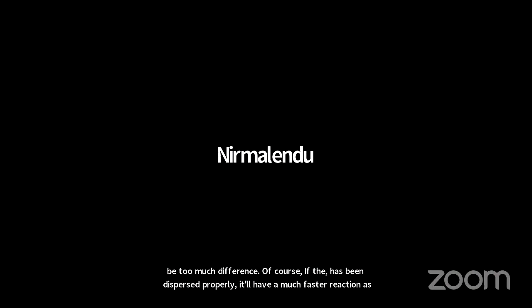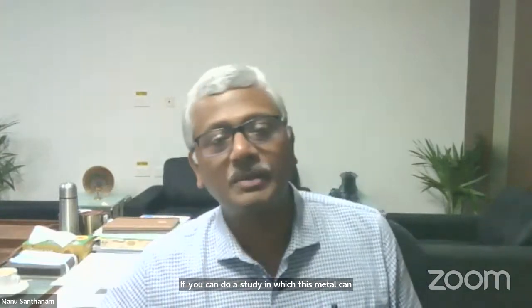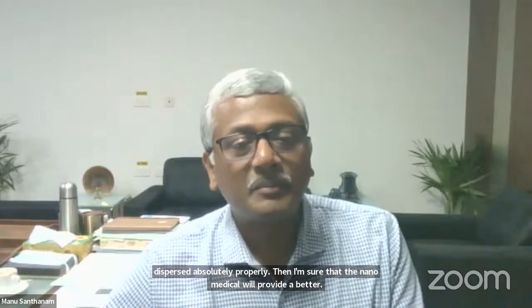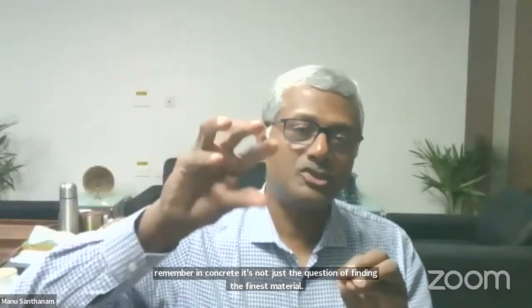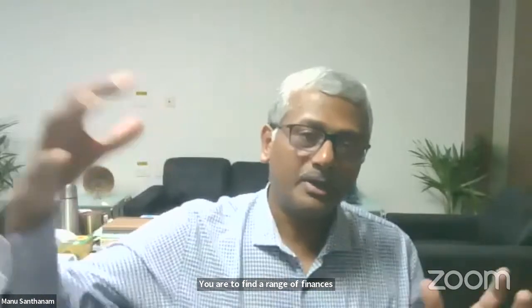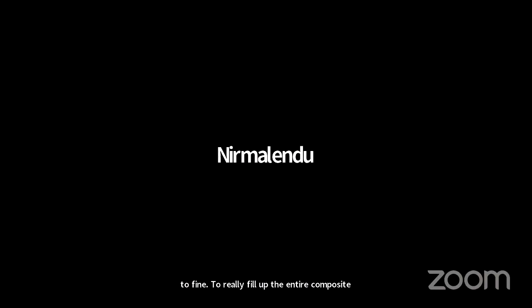Is there any pore refinement and grain refinement difference between these two? Well, again, see, the reason why the extent of refinement expected with nanomaterials is not always seen in research studies is because we have not had a successful dispersion of these materials. If you can do a study in which this material can be dispersed absolutely properly, then I'm sure that the nanomaterial will provide better space filling as compared to the micromaterial. But please remember, in concrete, it's not just a question of finding the finest material. You have to find a range of finenesses that go from coarse to fine to really fill up the entire composite volume. Particle packing. Yeah, exactly. Right. Thank you.